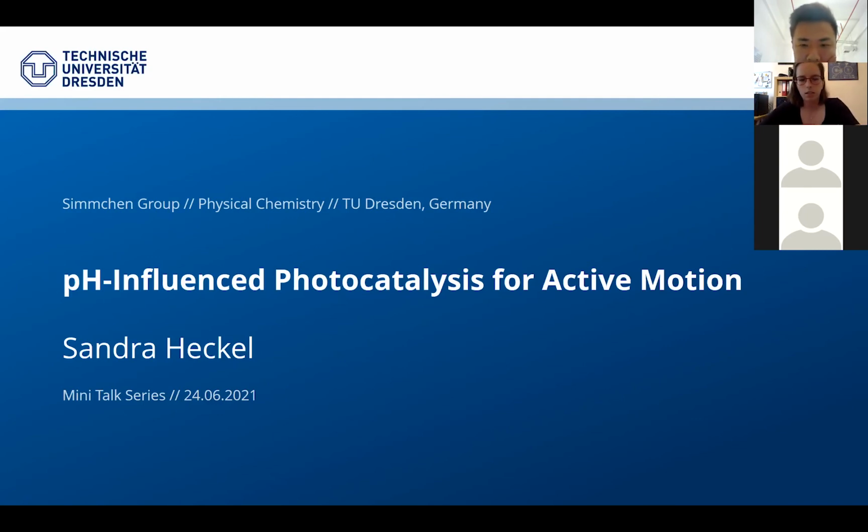Yes, I think I know what you mean. So usually they assemble at neutral and alkaline pH values, the spheroidal particles a bit more than the stacked ones. I think that's just because of the geometry. Below the point of zero charge, when they are charged positively, we still see that they assemble, but not that much anymore. But we didn't really look into this a lot. So I can tell you, yes, they do, but it seems it is a bit more rare.